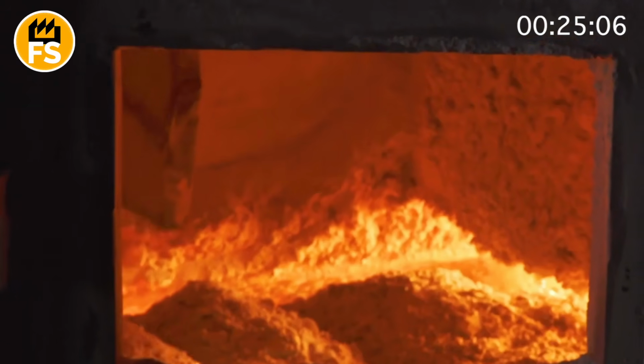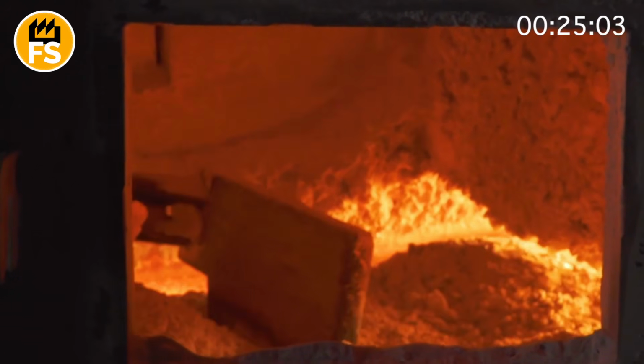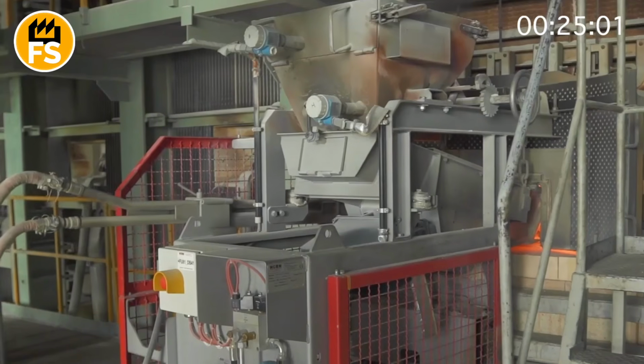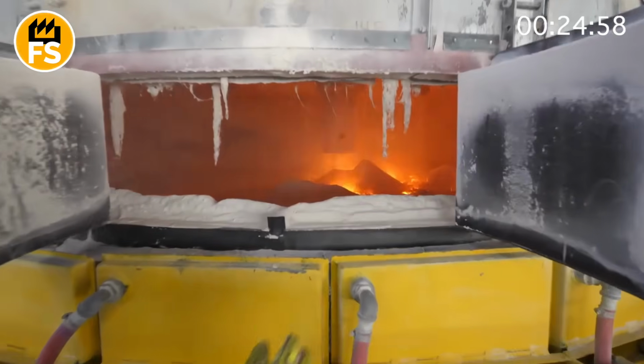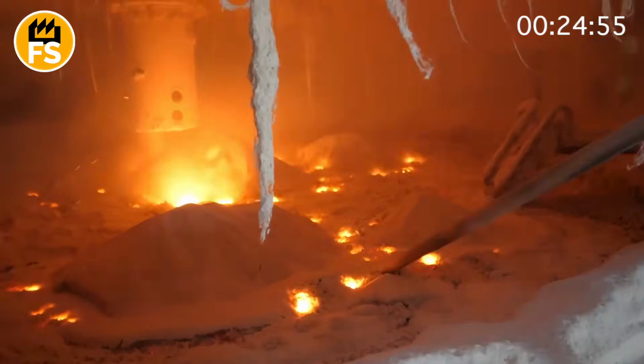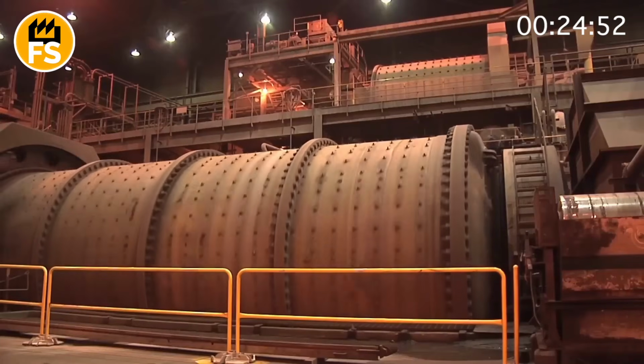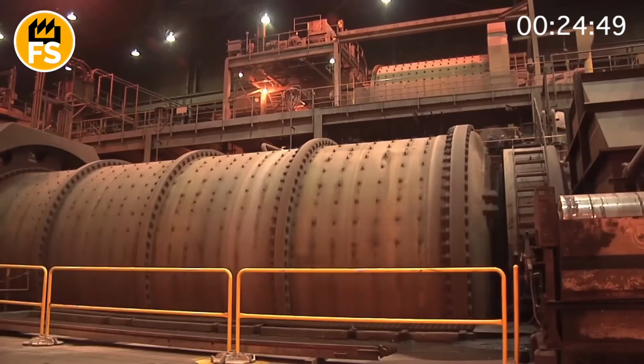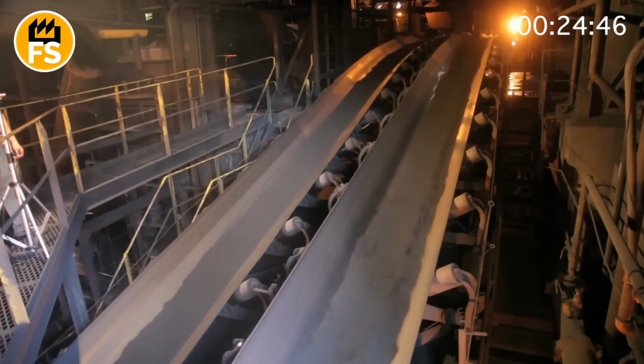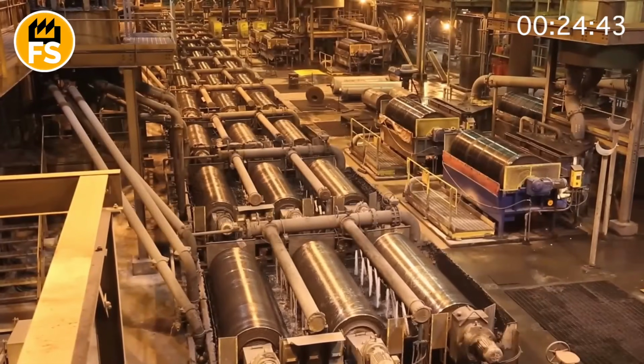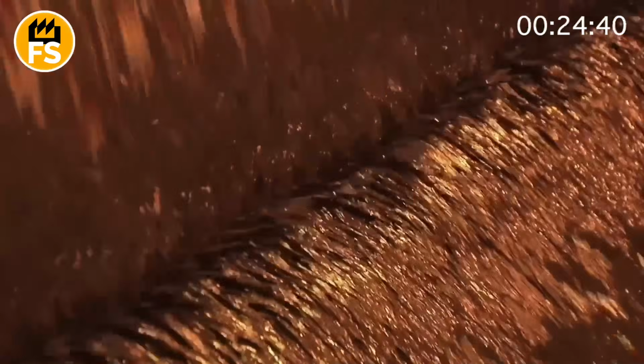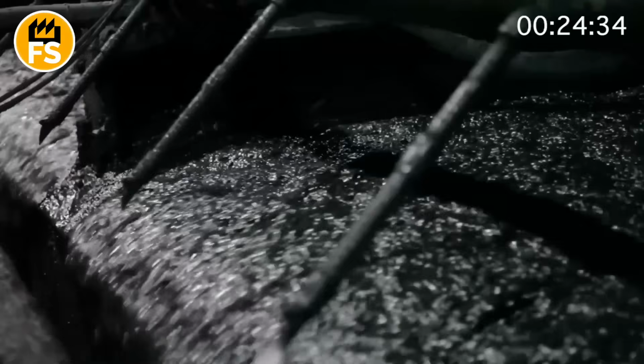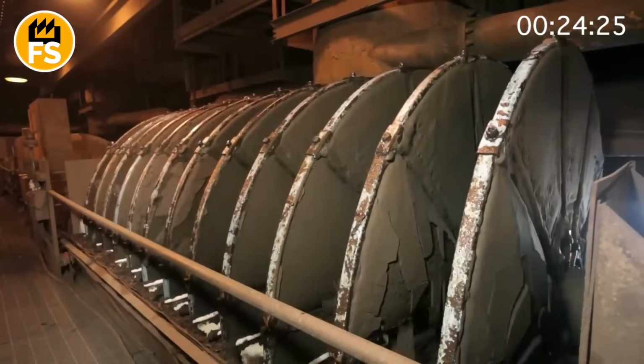After preparation, the raw mixture is poured into special furnaces for melting. This stage includes a few important steps, so let us review them together. Melting temperature. To create molten glass, a temperature of about 2,732 degrees Fahrenheit is used. Throughout the melting process, the raw materials transform into a uniform, viscous liquid. Homogenization. The molten glass is stirred to distribute components evenly. This is important for preventing air bubbles or other irregularities in the finished product. The furnaces for melting glass are equipped with modern systems for temperature control and process automation, which guarantee the high quality of the final product.